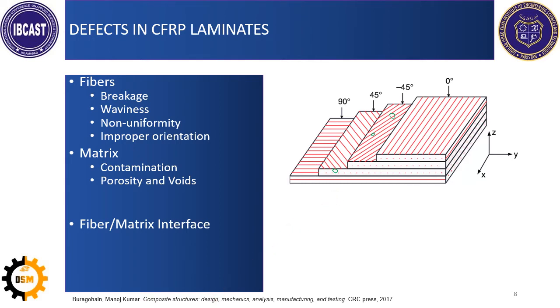It may happen. So if you are doing condition health monitoring, you will observe these voids in the beginning, and you will keep on monitoring those voids. If a void is slightly increasing, your SHM system will quickly tell you that there is a problem, and you will quickly reject that part if it is above the safe threshold. So porosity and voids is another problem in the matrix.